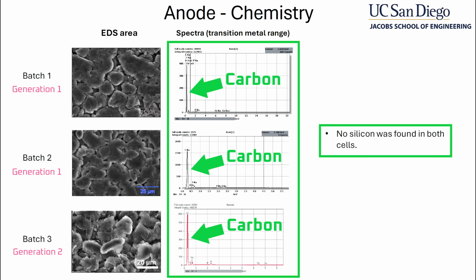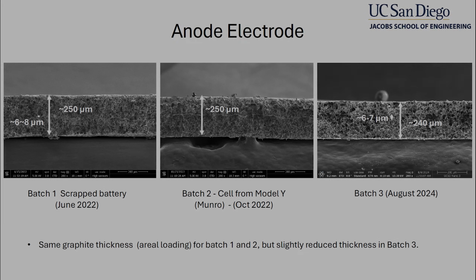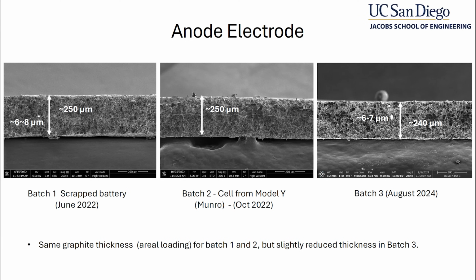Since the anodes in the Generation 1 and Generation 2 4680 both use pure graphite, on a weight-for-weight and volume-for-volume basis, the energy density of the anode in each battery cell should be nearly identical. That piece of information can be used to guess the energy density of the cathode material. How? Let's start by comparing the thickness of the anode material for each 4680 that UC San Diego has tested. Both of the Generation 1 4680 cells had a total anode thickness of 250 microns, whereas for the Generation 2 4680 it was 240 microns.